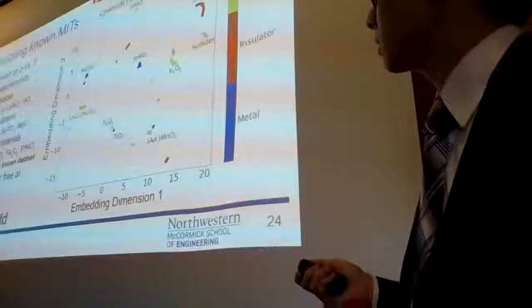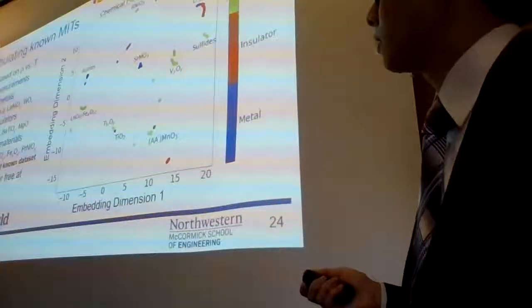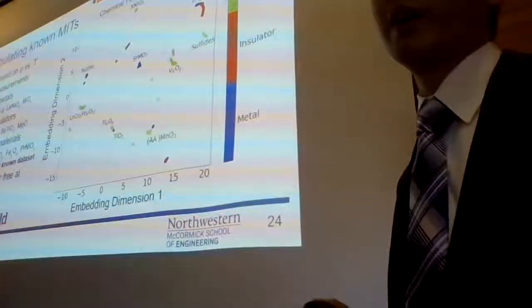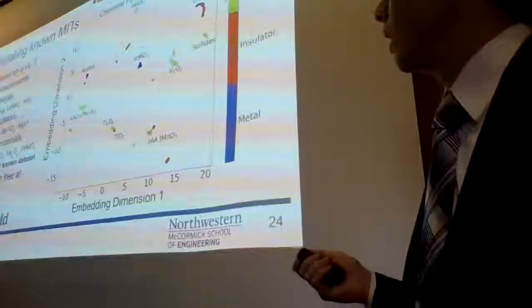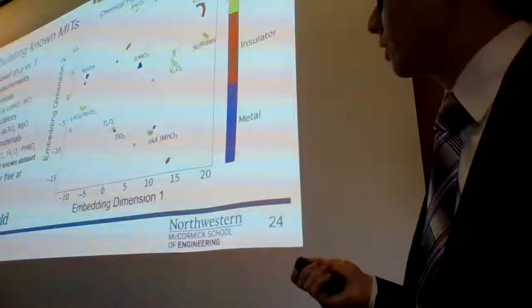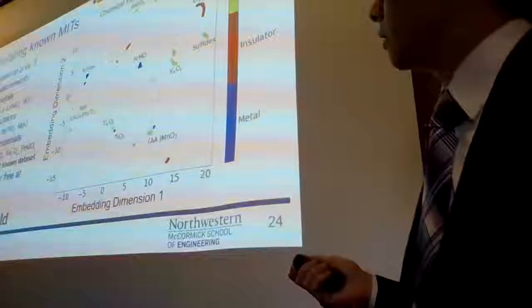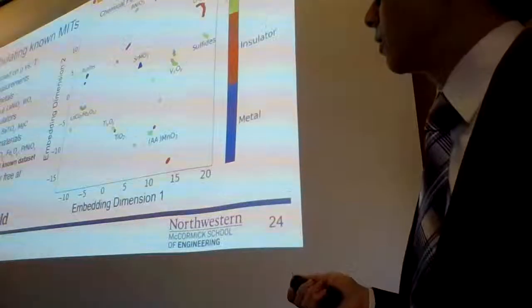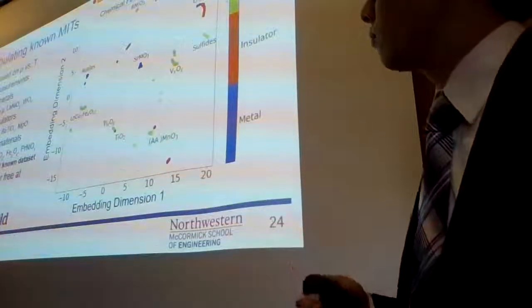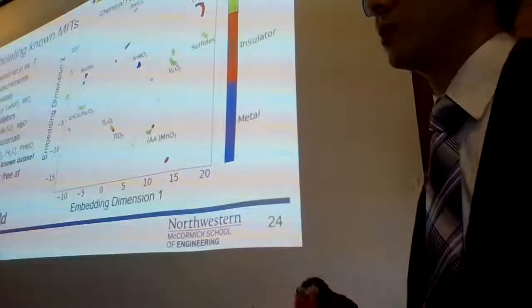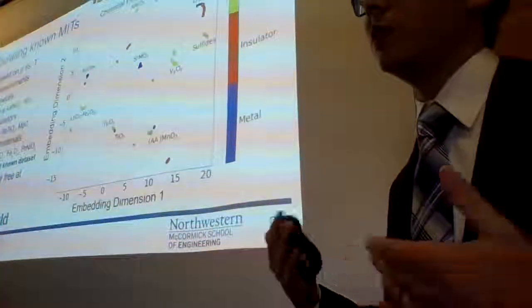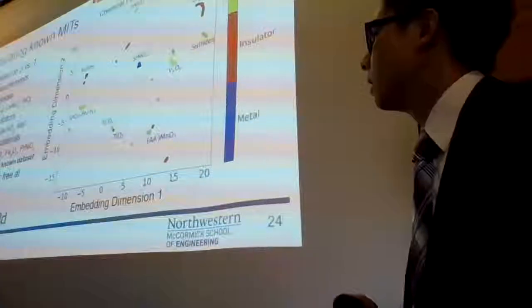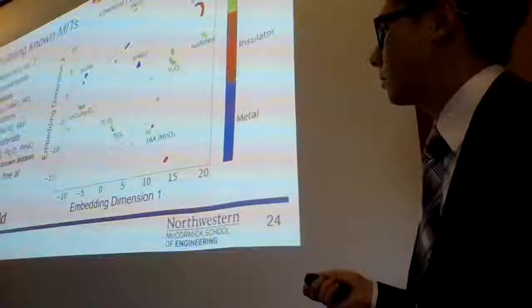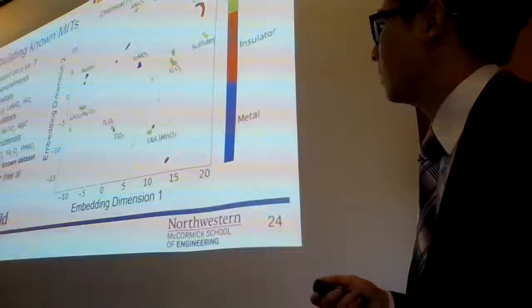So unfortunately, my data set is rather small in size because it's culled by hand from experimental reports. But I had a number of metallic oxides, a number of insulating oxides, and to the best of my knowledge, one of the largest metal insulator transition data sets with transition temperatures and resistivity values across the transition. And I put it up on this data hosting website called data.world.